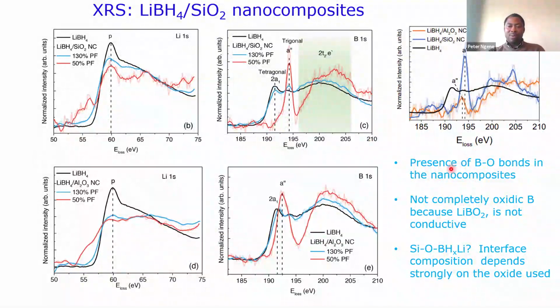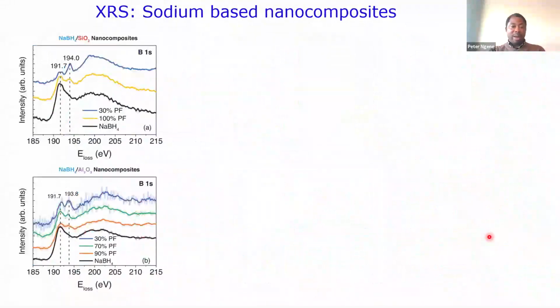So what we can conclude is that we have something like BO bonds in the nanocomposites or tetragonal boron, but we can say that this is not completely oxidic boron, because LiBO2, like I mentioned before, is not conductive. So we think that at the interface we have something like this, because the surface of the metal oxide contains a lot of hydroxyl groups. So we think there's some kind of interaction happening at the interface where the boron is close to the oxygen. And somehow this also affects the chemical environment of lithium, because we can see here that this oxidic kind of lithium environment is quite different from the bulk-like material. So this is what we can conclude on this.